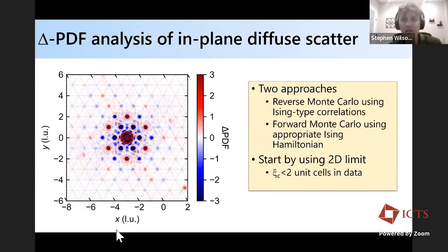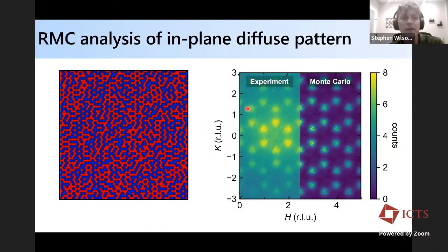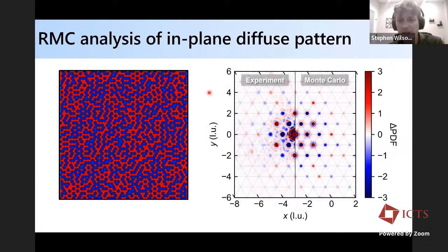Okay, so for the in-plane diffuse scattering, we can do two things. We can do the reverse Monte Carlo and also forward Monte Carlo. If we assume a two-dimensional limit, which is reasonable in this case because the correlations between the planes are very short range, then we can start with the reverse Monte Carlo analysis. From that, you can get a pattern that matches the experiment. What's generating this pattern of scattering are these zigzag correlations within the plane, assuming just an Ising degree of freedom, up and down, of the tin atoms. You can compare the delta PDF map, and I don't have time to go through all the details, but it matches to a good degree, okay?